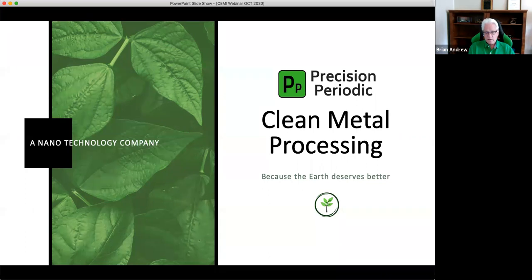It's very cheap, and then you pull out your gold and silver in one process. Because all we've done is pull the gold and silver out of the leachant, you can put it back in the dirt for the next cycle, and you keep doing that. Now, the thing about using hypochlorous and a salty leach liquor is you generate salt. Sodium chloride begins to build up as well. If you get too much sodium chloride in your leach liquor, you can't use it anymore. So that's after about 50 cycles.